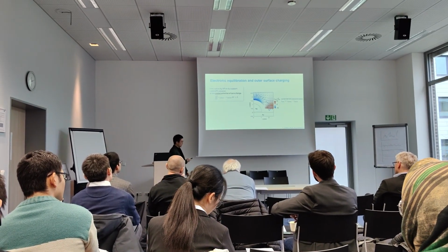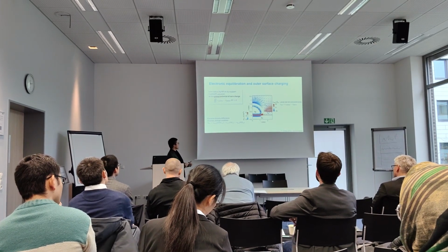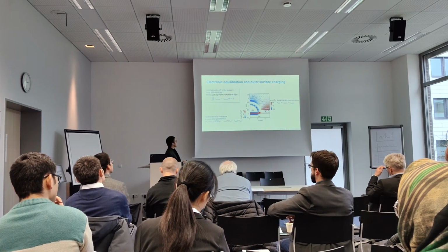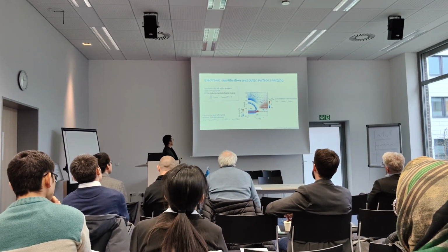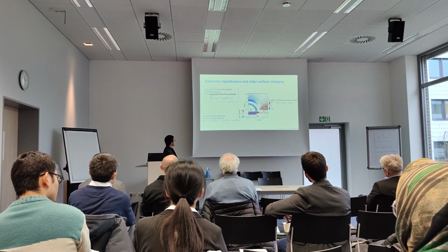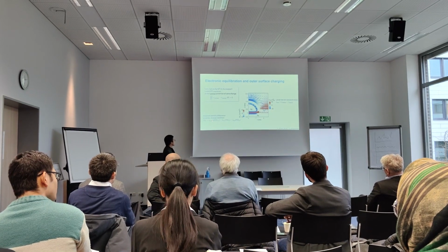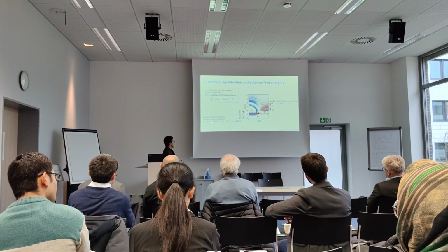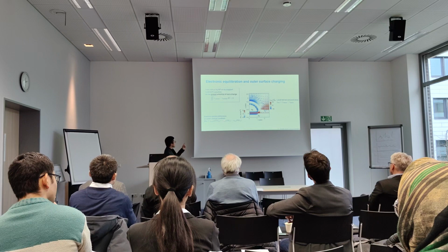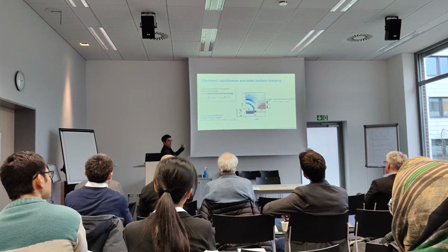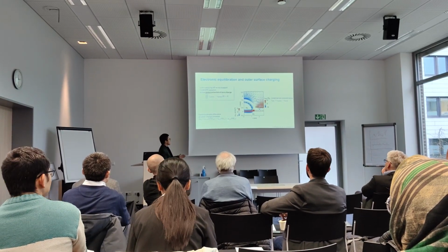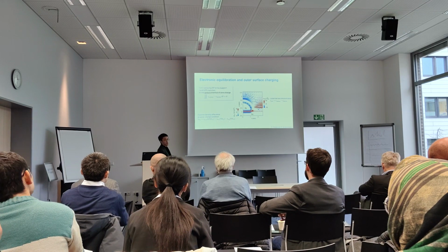of the electron redistribution across the whole system because of the difference in Fermi level. This electron redistribution is quantified by the electron density difference at this constant charge condition. It is the electron density of the combined catalyst-support system at its own charge neutral state, minus the electron density of the unsupported catalyst system at its own charge neutral state, minus the electron density of the bare support system at its own charge neutral state.